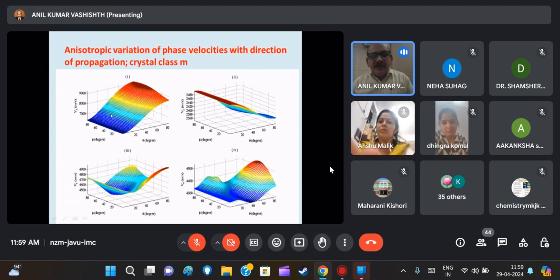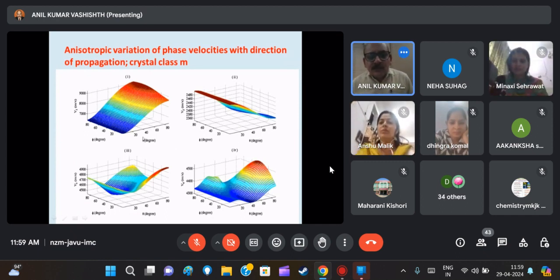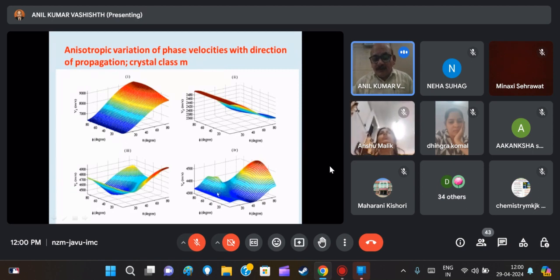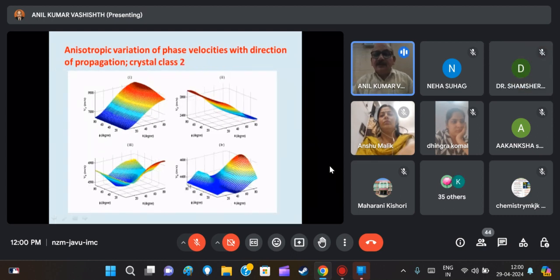and the direction dependency of the phase velocities is very much clear from these three-dimensional plots of the phase velocity, where we have changed theta and phi, longitude and latitude, to show how the wave velocities of the four waves behave. This is something very interesting, that V2, the slow wave, is due to the solid phase in the porous piezoelectric material, and V4 corresponds to the charge propagating in the form of wave solutions, that is the electric potential phi, its velocity. So these two results, V2 and V4, were different, and they are new.